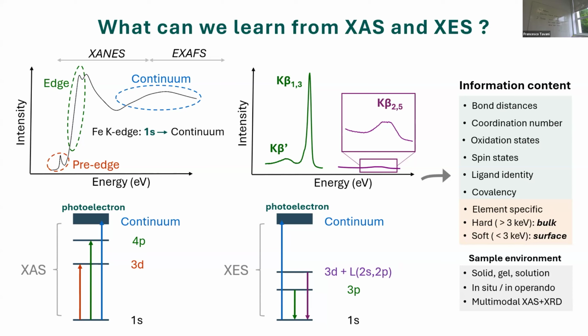So XANES is extremely sensitive to the local geometry, like the coordination number. If you have a 5 coordinate compared to a 6 coordinate, it will be very different. Also, a perfect octahedral 6 coordinate compared to a 6 coordinate where the octahedral geometry is for some reason distorted, these peaks will be very different. With XANES, on the other hand, you will not really be able to identify the bond distances with high precision, so there will be an error on that. EXAFS, on the other hand, is very sensitive to the bond distance. So you can have an EXAFS analysis that identifies the bond distances with, I think, 0.01 angstrom of error.